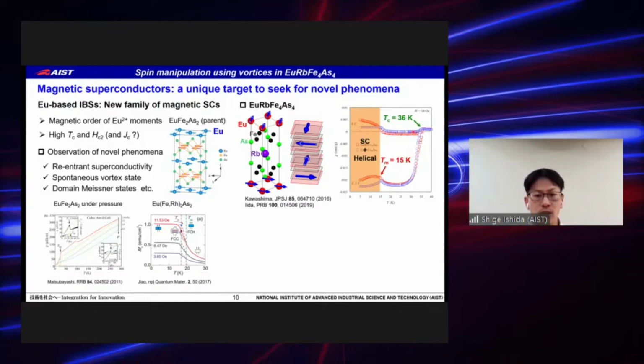In addition, a neutron diffraction study revealed that europium moments align ferromagnetically in the AB plane, and the orientation rotates by 90 degrees in the next layer. Namely, the ground state is helical, like this.